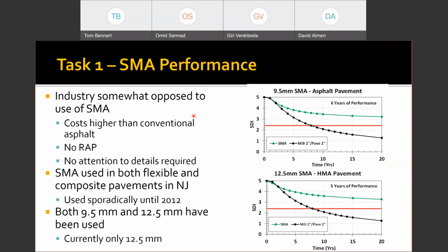Because if you don't, the construction process can be a little bit challenging. But what we found, again, going back into the pavement management system, is that when we're putting these on flexible pavements, now non-composite, putting them on traditional asphalt pavements, you can see the improvement in life over your typical dense graded mix, whether it's a 9.5 or 12.5 millimeter SMA. We're talking 5, 6, 7 years easy of a life extension over these pavements.